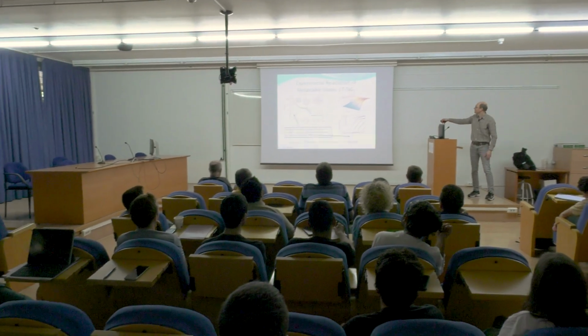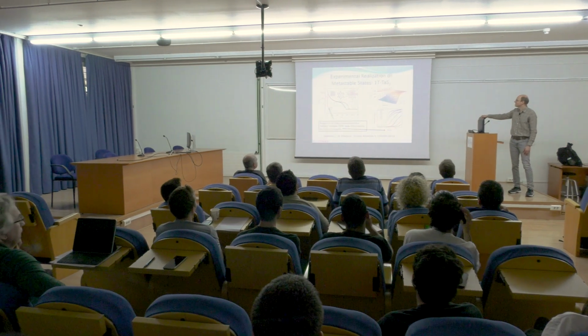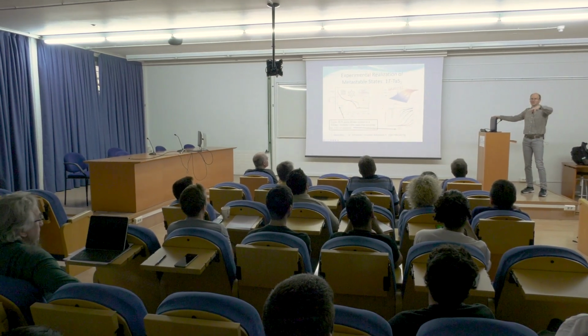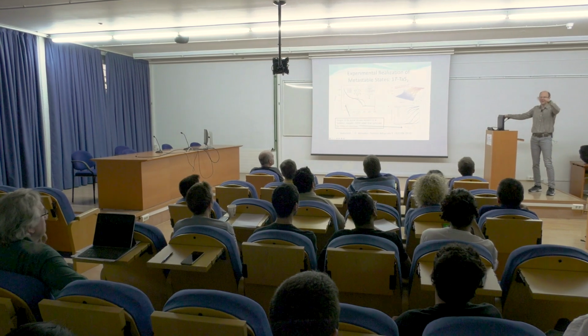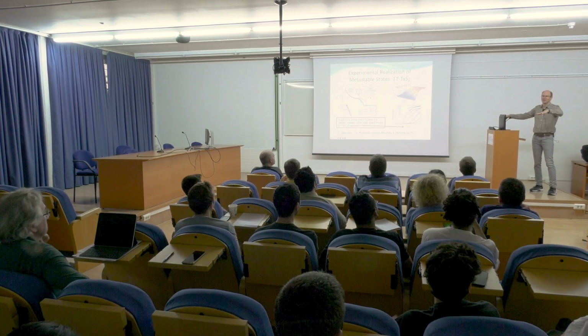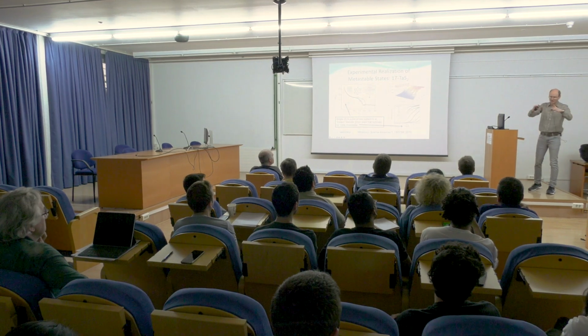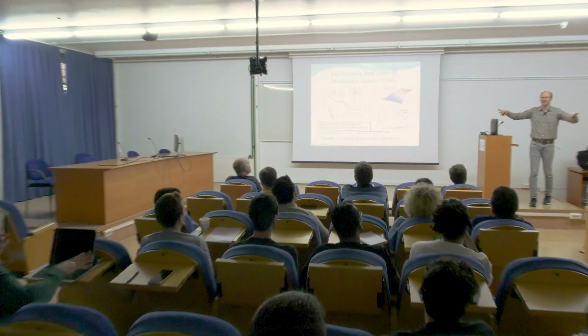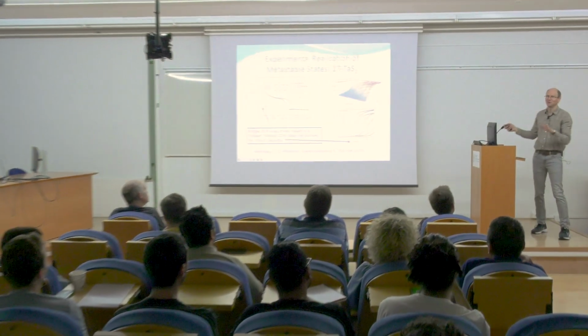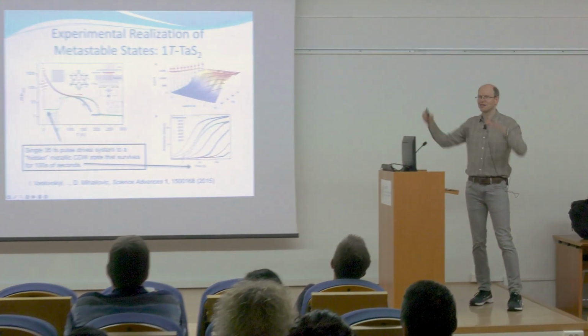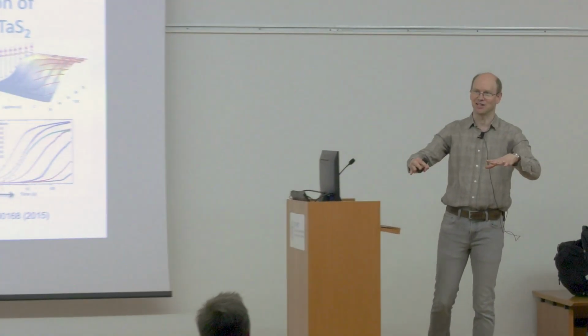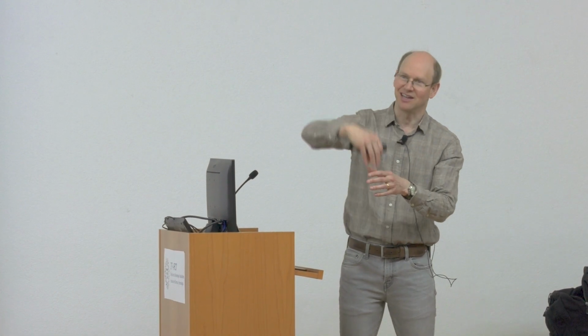Yeah, so the spot size of the laser that's incident is larger than this region. So it's inducing that order just underneath where the laser is illuminating the system. I don't know how much detail is known about how it propagates outside of that laser. It may be known, but I don't know that. But you can think of this as just occurring under the spot where the laser is shining. And that's going to be the typical scenario: you have a material in many cases which is bigger than the spot size of the laser, but you measure the changes at that spot size, or where the laser spot is.